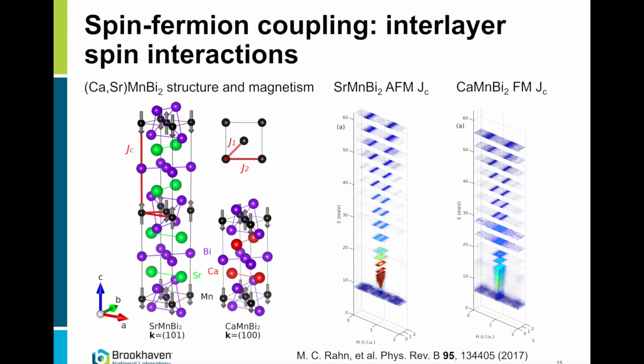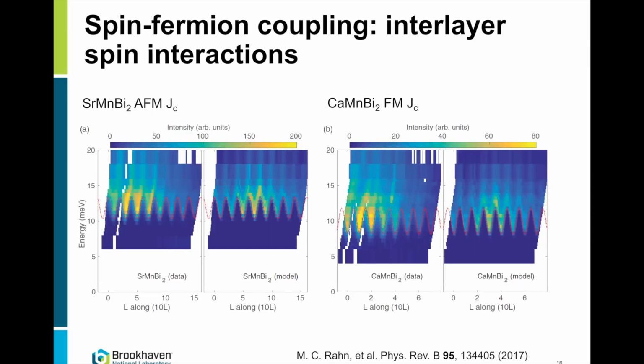And what they have shown is that switching from strontium to calcium, the interlayer coupling switches from antiferromagnetic to ferromagnetic. And you can see that by measuring the interlayer dispersion. So this is a dispersion of spin waves, and the dispersion in the interlayer direction is not very well seen here. So this is another view of the dispersion in the interlayer direction in strontium-manganese bismuth 2 and calcium-manganese bismuth 2.